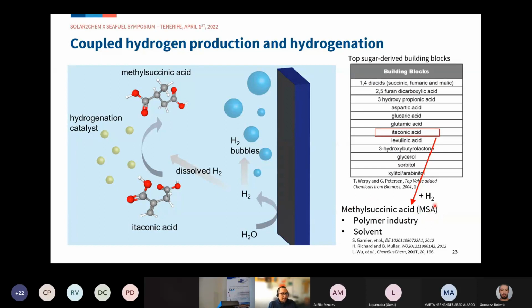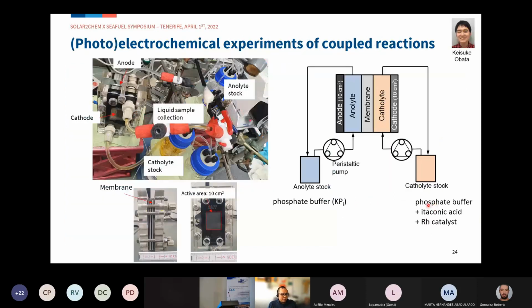To test this coupled concept, we performed an experiment using simple electrochemistry. We have the anolyte and catholyte separated by a membrane. At the anolyte, we have a potassium phosphate buffer since we're just doing water oxidation there. But at the catholyte side, we have a phosphate buffer filled with itaconic acid as the substrate and a rhodium catalyst as the hydrogenation catalyst in homogeneous form.